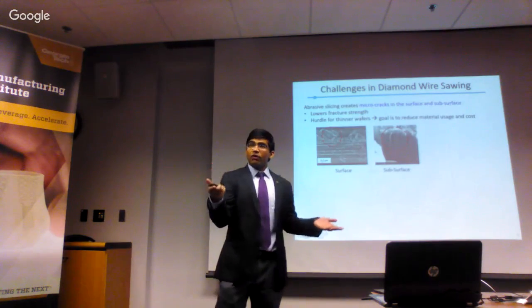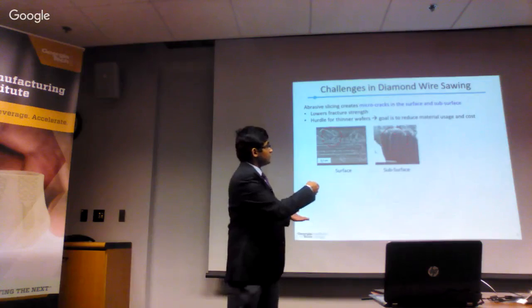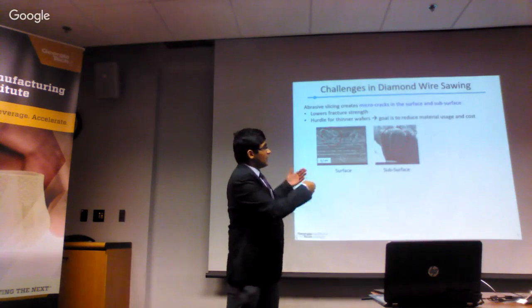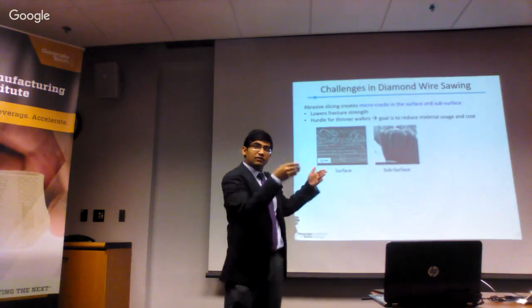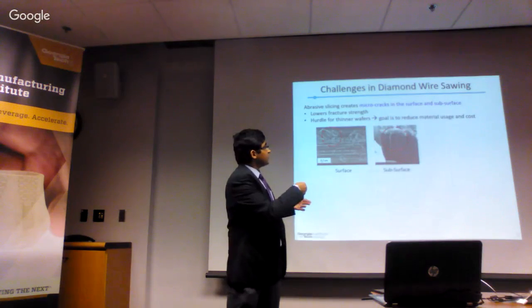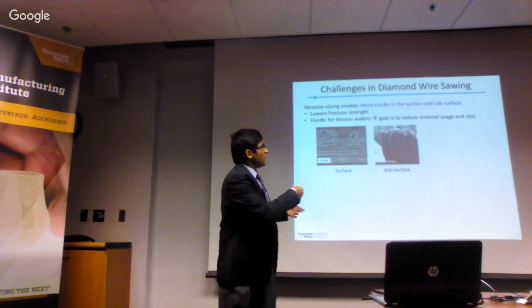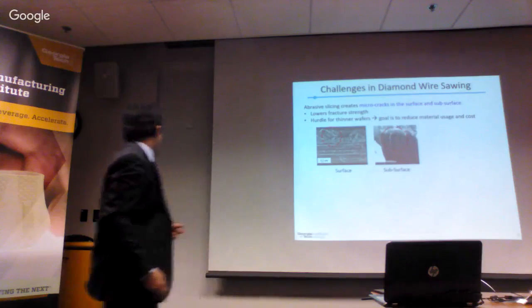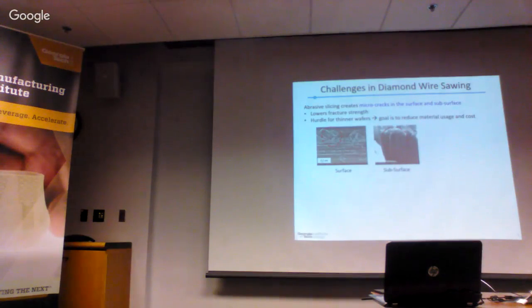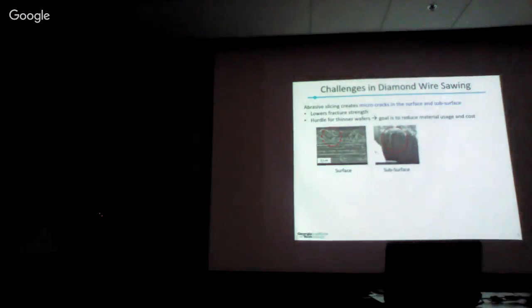The micro cracks are also on the subsurface, as you see here. This is a FIB cross-section of the subsurface. The top part is the surface, this one is the subsurface, and you see here the micro cracks. In the interest of seeing the images better, I'll put the lights off, and you can see more clearly the micro cracks on the subsurface.